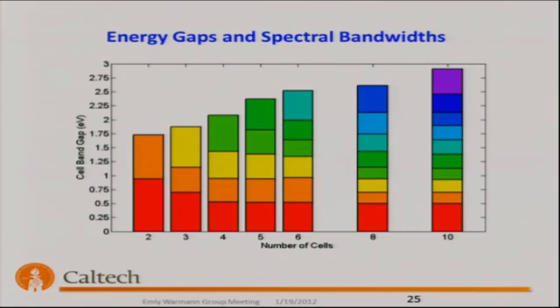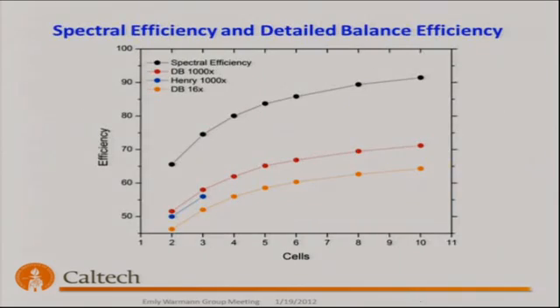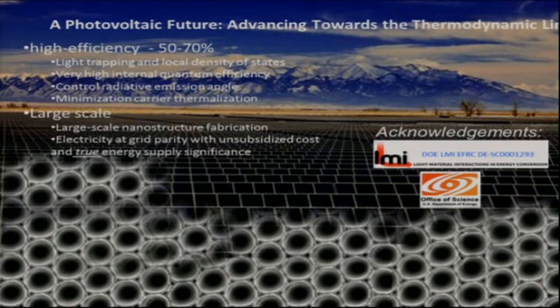And this just shows the arrays. You can calculate the arrays of band gaps and spectral widths. It's a beautiful engineering optimization problem. And you can go back to detailed balance calculations and convince yourself that with modest concentration, you could get well over 60% efficiency in such a structure. So we think there's a new regime of photovoltaics at hand in the 50 to 70% efficiency range. That this is really the target we ought to be aiming for.